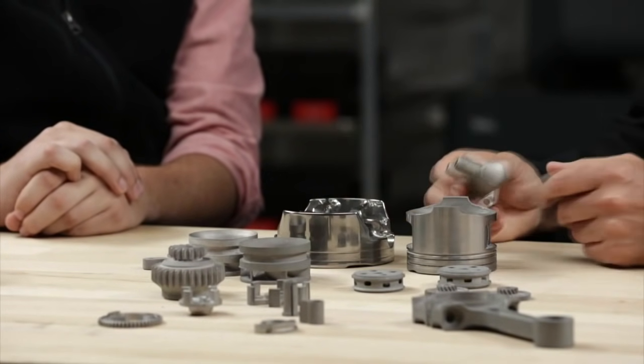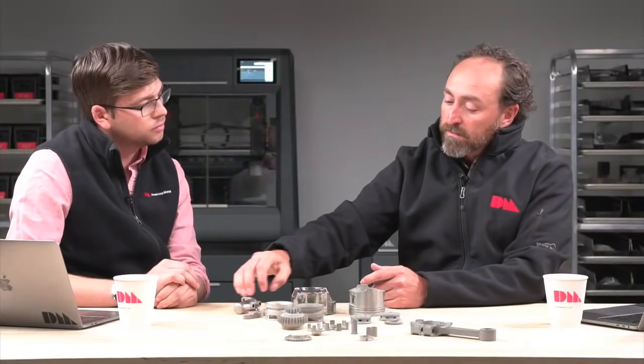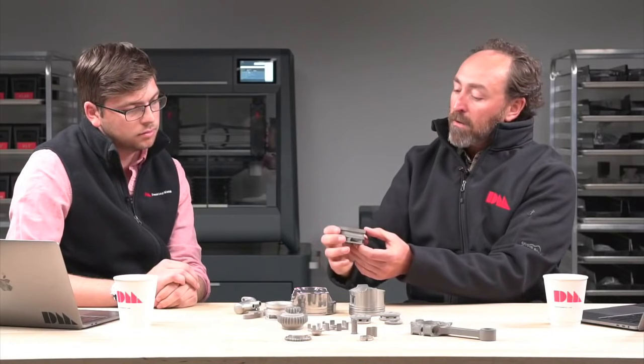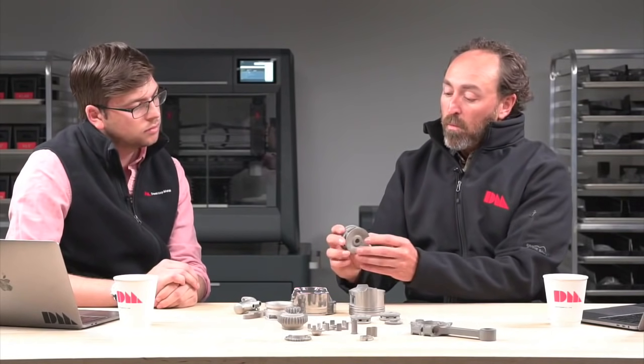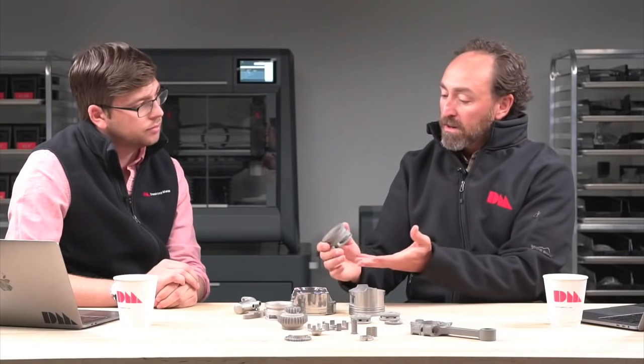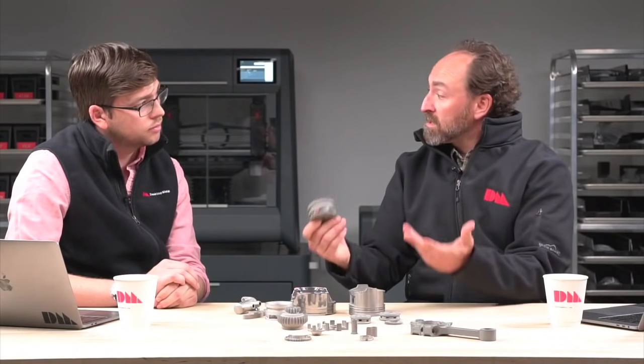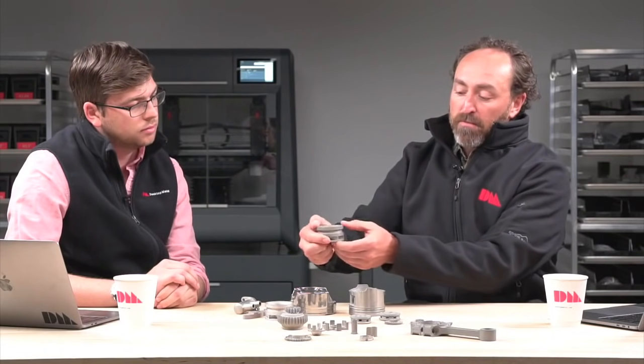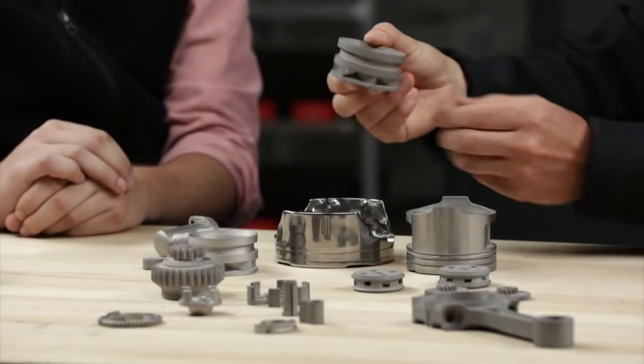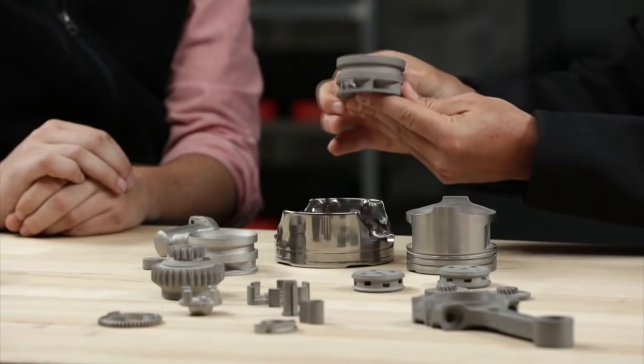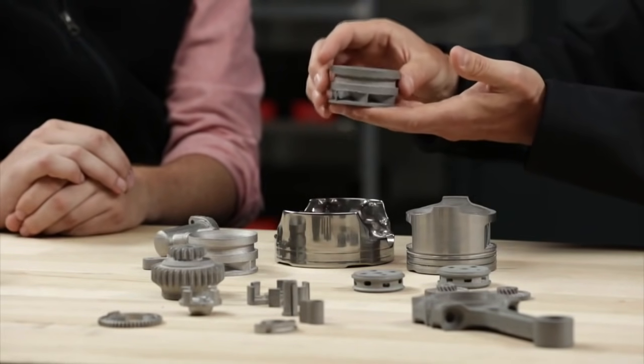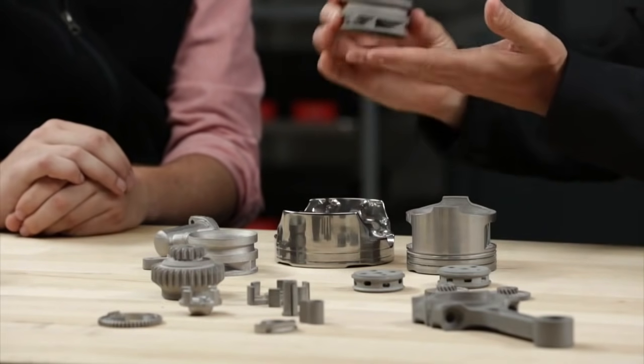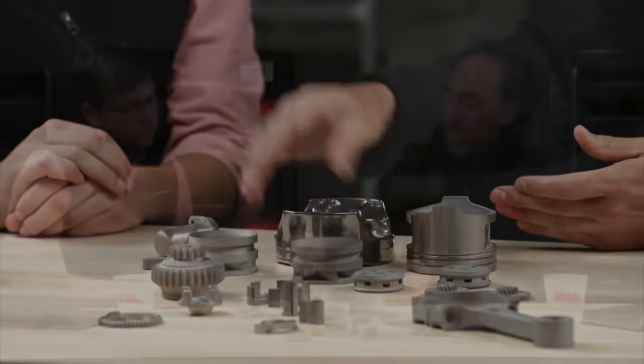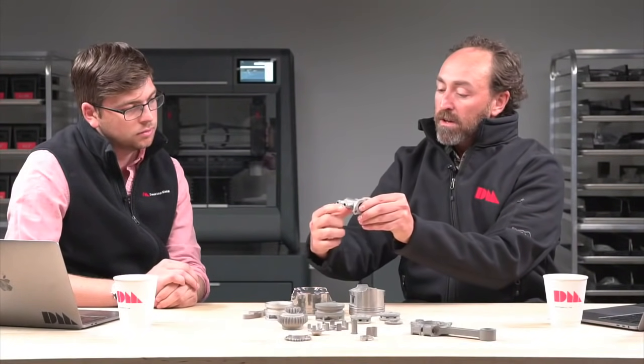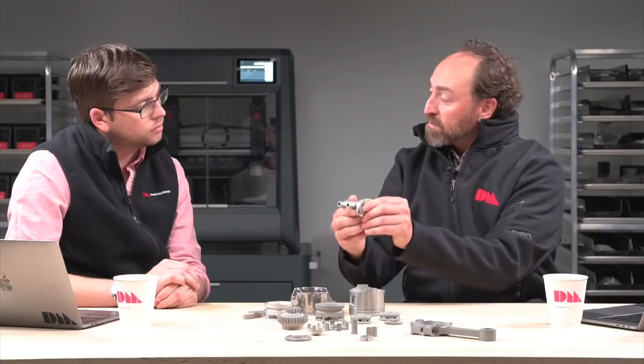Now the production system is slightly different. The production system prints parts in a powder bed, and so the powder acts as those supports. Now, what you need to keep in mind is that just because you've printed it without supports doesn't necessarily mean you can sinter it without supports. So a part like this that was printed in the production system doesn't require supports in these channels because of the powder that sits there. It becomes stable, but it's also self-supporting in the sintering furnace. Meanwhile, a part that you might print with a 90-degree angle might be printable, but would require supporting in the sintering furnace. And so there's subtleties like that.